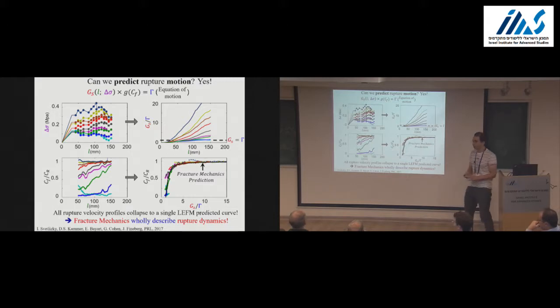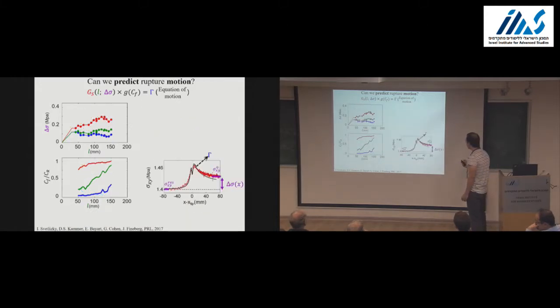Do you have any friction at the tail for your fits? The stress drop is defined between the initial stress with respect to the residual value. Following Rice's work in '68, because of the linearity of the equations, you can essentially subtract the residual value at the tail.